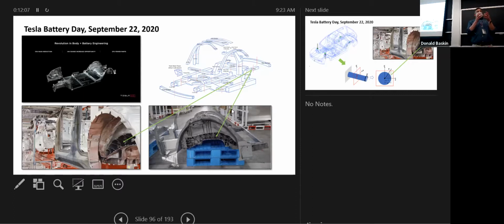But this is exactly right. Where the loads would be the highest in torsion, on the outer skin of what is effectively a tube, they've taken the material off. So they've taken material off where the stress would be the highest. And the way they have to make up for that is probably by putting more material inside in order to get the stiffness back. They probably did this because of the way they cast the part. I don't exactly know what they did, but they cast it in some orientation where they have to take the mold out, and if it were closed off, they might be die locked and wouldn't be able to get the part out. So I'm sure the engineers at Tesla thought about this, and they had a compromise to make this part out of aluminum.